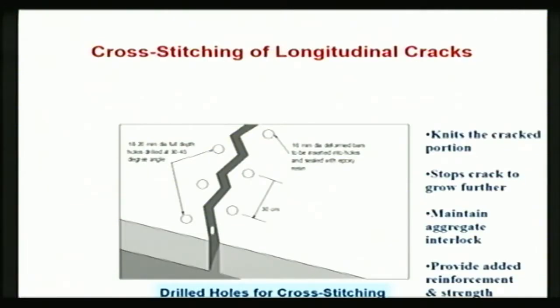This is cross stitching. Cross stitching is always used for longitudinal cracks. Any longitudinal crack, before it opens up too much, you have to fix it. You have to cross stitch it. Cross stitching will not prevent further occurring of the crack. What it will do, it will keep the longitudinal crack intact, in a very close form. It will not allow it to widen further. Cross stitching is never done for a transverse crack, because transverse crack movement is allowed, but we do not allow movement at longitudinal cracking. That's why for longitudinal cracking we go for cross stitching.